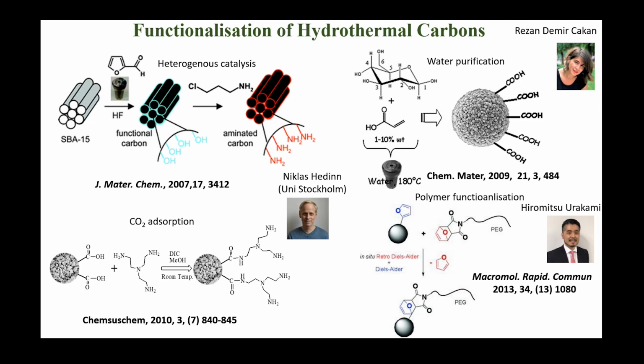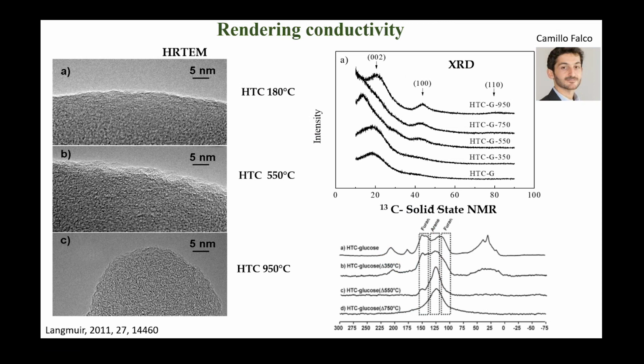So now all these materials are made at low temperature. They're quite stable, but they're not conductive. So they're great for applications in water purification, for example, or in this paper, we have a porous carbon material functionalized with a lot of branched amine groups, which are great at capturing CO2. This is some old work, as I said, we've never come back to it, but I would quite like to maybe come back to these concepts and start working maybe again on CO2 capture or direct air capture, but I never got around to it because meanwhile I got interested in batteries and electrocatalysis, and so I was always trying to make them conductive.